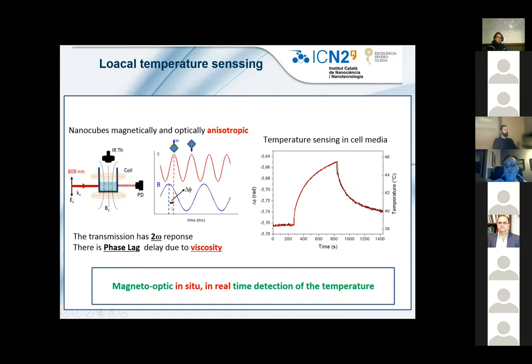And there is another effect, which is that the optical response usually has a phase lag relative to the magnetic field. This is because of the drag of the nanoparticles inside the liquid, and this phase lag is due to the viscosity. And since viscosity depends on temperature, by measuring this phase lag, we can measure temperature. Here I show you an example. We put the nanoparticles in cell media and we apply the AC field. Here in red, I show you the phase lag, which is the difference between the absorption and the magnetic field. And in black, I show you the temperature we measure using a different thermometer. You see that there is a very nice correspondence between both measurements.